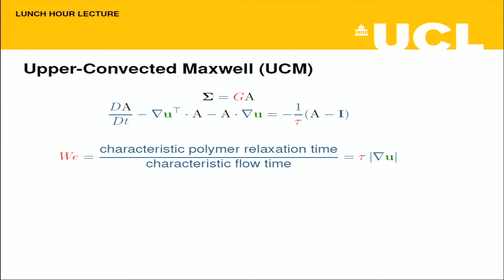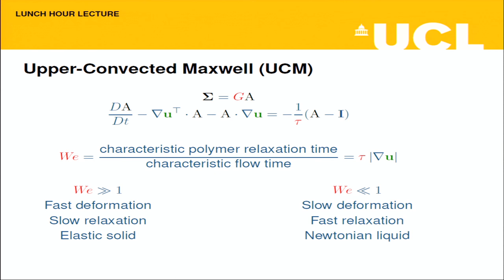The Weissenberg number can be understood by its extremes. Large Weissenberg number means very fast deformation or very long polymer relaxation time — the conformation stays for a long time and doesn't relax out, giving behavior rather like an elastic solid. Small Weissenberg number means very slow flow or very quickly relaxing polymer — whatever you do to it, it returns to a sphere quickly and you get just fluid-like behavior.